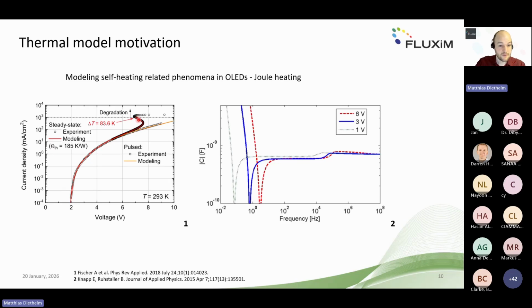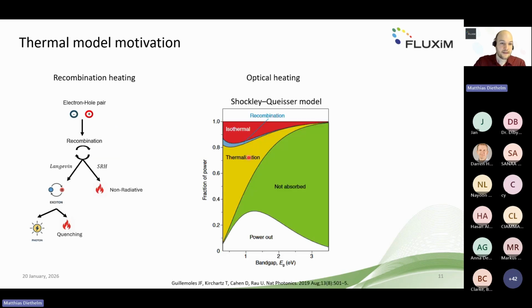But even before this effect, if I go to lower voltages, where the current starts to rise slightly, you see these changes already in impedance spectroscopy features, for example, as another low frequency feature you can see here. To model this, you need this self-heating, you need Joule heating. That's the first aspect of the thermal model.